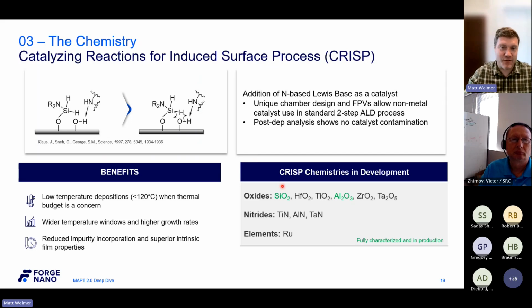Again, we have our flagship CRISP process for silica. We have one for alumina, but to be quite honest with you, the TMA water process is so robust that it really only matters once you get below 110, 105 degrees Celsius. But we have it for other oxides. We're certainly exploring things that aren't quite as mature, like nitrides, but I think there's a lot of potential here. And we do have quite a good metal film that takes advantage of this. Fortunately, I can't talk about the specific catalysts because that's where our IP lives.